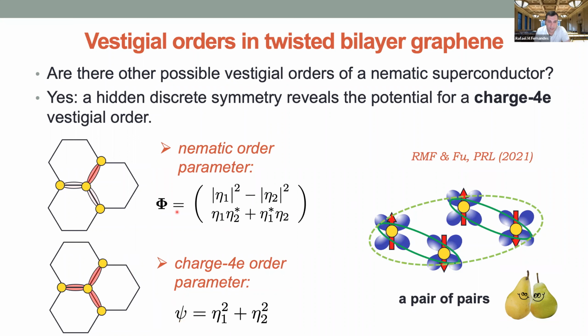This is a composite that, in principle, as long as I have 2 condensates, I can have it. But the question is, is there any chance that this can condense instead of the nematic? What we found in this paper with Liang Fu is that actually there's a hidden symmetry that connects these two. This is a 2-component real order parameter, and this is a 1-component complex order parameter.